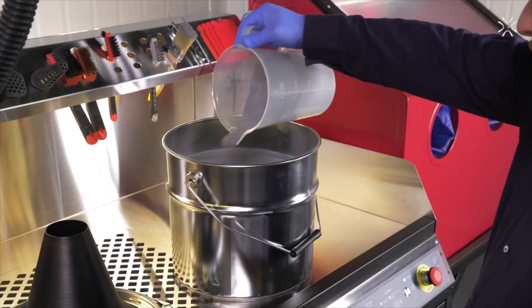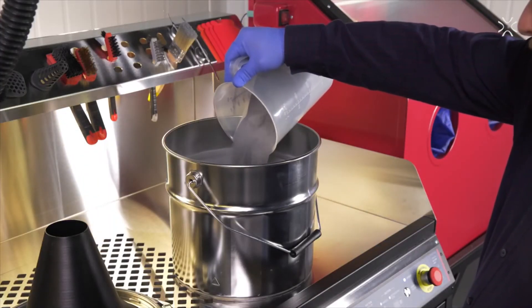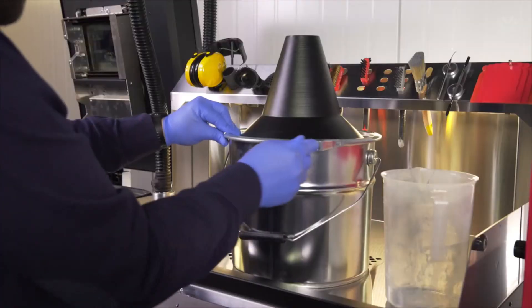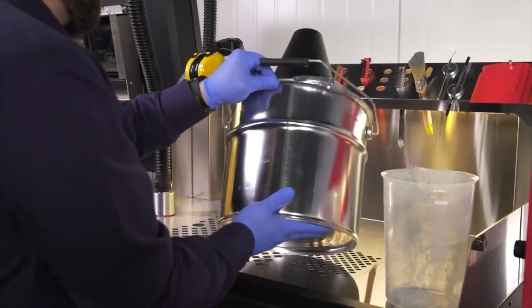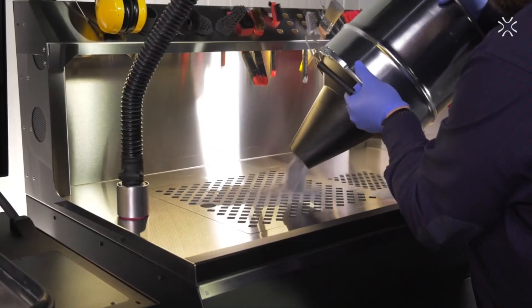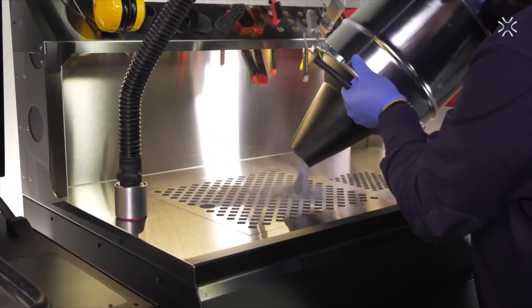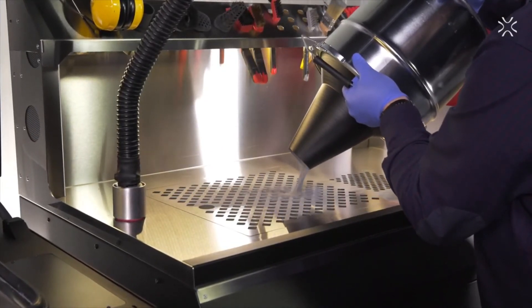Add a proper amount of fresh powder to the sifted recycled powder. And then put this mixture into the powder chamber. Remember to turn off the vacuum and PHS. You should repeat this process two to three times to get a homogenous mix of powder.